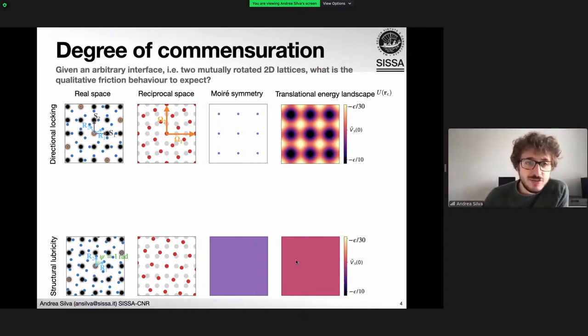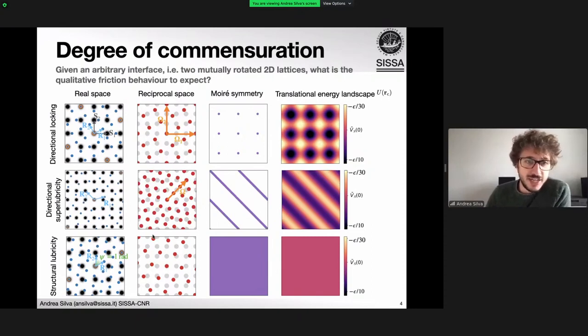And in this categorization, we discover an intermediate novel type of interface, which we call directional superlubricity, because for specific lattice symmetries, you would have only one coincidence lattice vector, and the moiré pattern would be formed of dense lines spaced over discrete spacing, which results in this energy landscape, which is made of valleys and ridges, where the friction is exactly zero along this valley, but retains a finite value perpendicular to it.